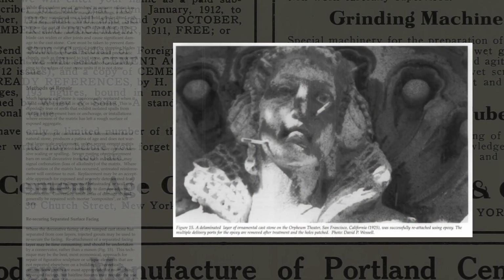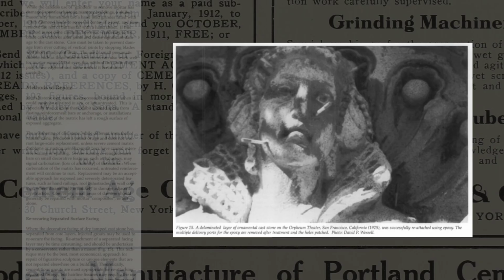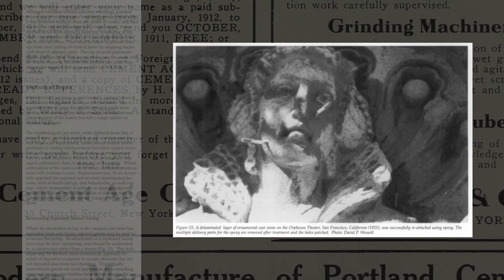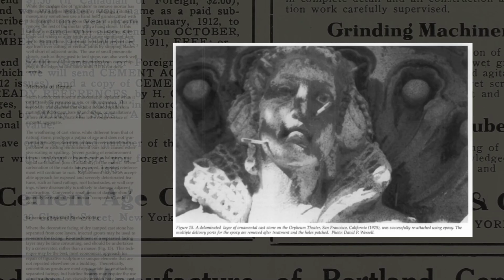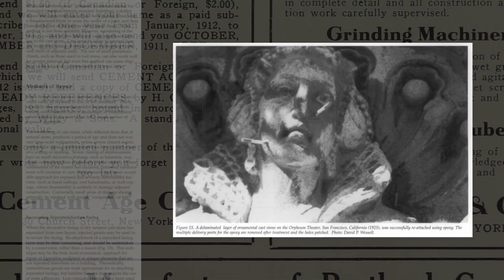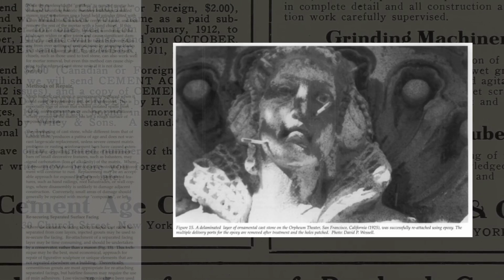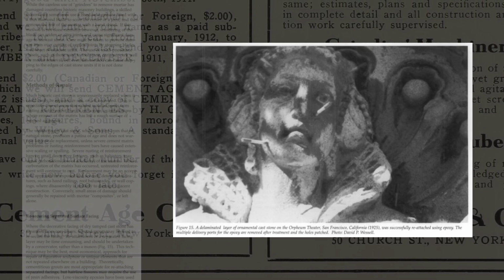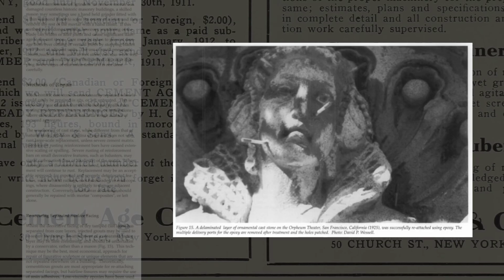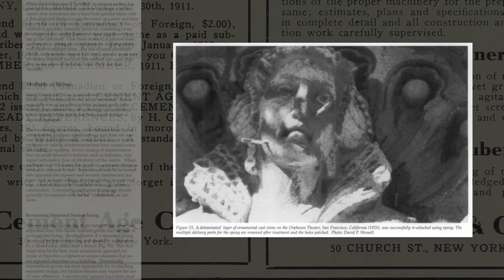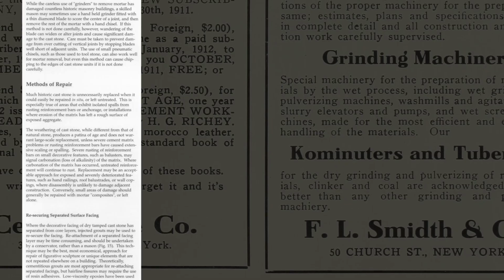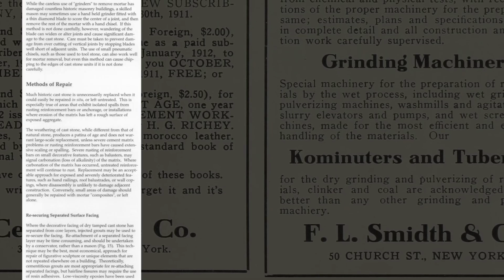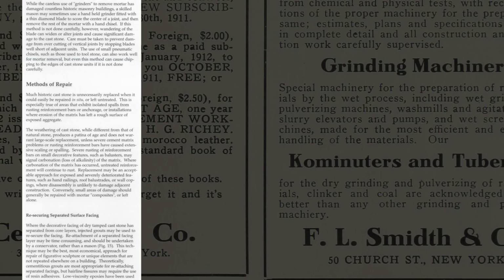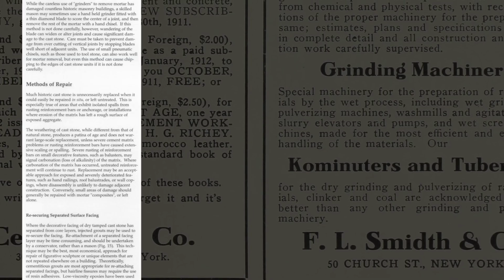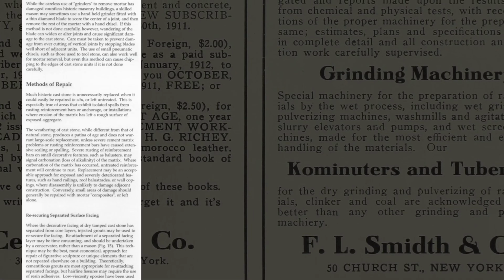And so here we have figure 15, and it reads as follows. A delaminated layer of ornamental cast stone on the Orpheum Theater, San Francisco, California, 1915, was successfully reattached using epoxy. The multiple delivery ports for the epoxy are removed after treatment and the holes patched. Continuing on. This technique may be the best, most economical approach for repair of figurative sculpture or unique elements that are not repeated elsewhere on a building.